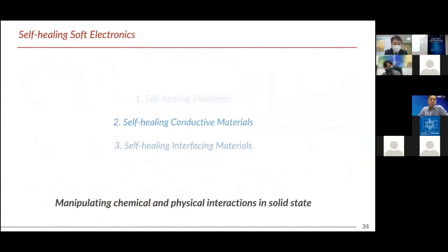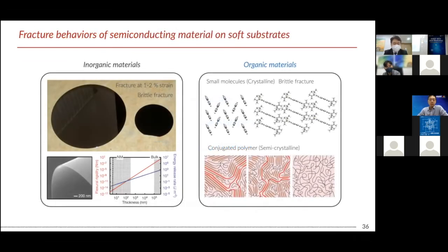So now I'd like to move to the last part, about how we can use the self-healing materials in stretchable electronics as interface materials. Initially, my starting point is that I would like to make a stretchable semiconductor. Most of the semiconducting materials are quite brittle, even the organic materials. Basically, conjugated polymers have received great attention for stretchable semiconductors because of their semi-crystalline behaviors. But even with conjugated polymers, they easily show some micro crack formation at 20% strain.